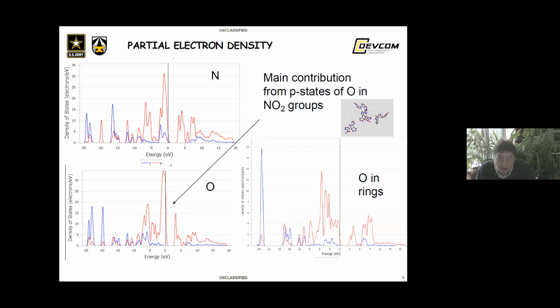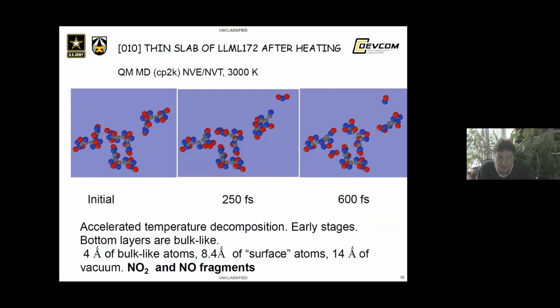So these are calculations of perfect crystals, but explosive solids are not perfect crystals. The solids have defects, and the higher the concentration of defects, the higher the sensitivity of explosives. The most common defects are voids and cracks. Obviously, I can't model a 50 micrometer void presented by Dana Dlott in his talk, but I can calculate the surface of LLM-172, hoping that it is a reasonable model for the inner surface of a big void.